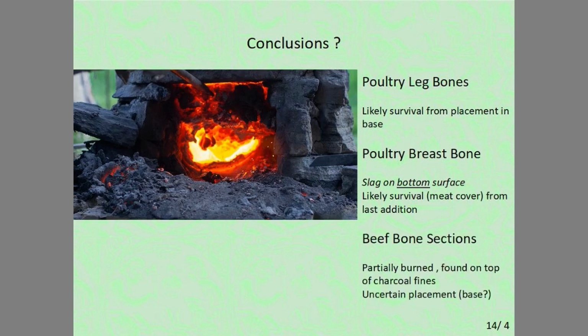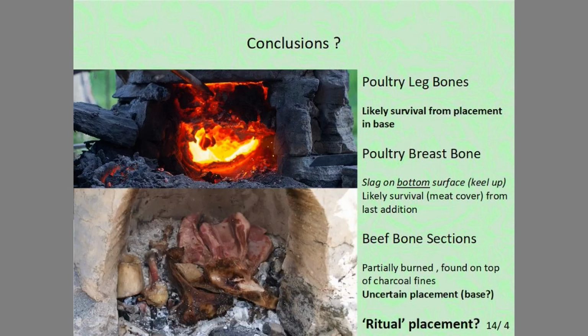The beef bone pieces were only partially burned. Their location found on top of the charcoal fines, but within the ashes, suggests that they may have been part of the last addition of bone, but this is actually uncertain. Taken all together, this suggests that the best survival of bone may come either from a very last addition before burn down or from bones placed in the base of the furnace, suggesting a possible ritual use.